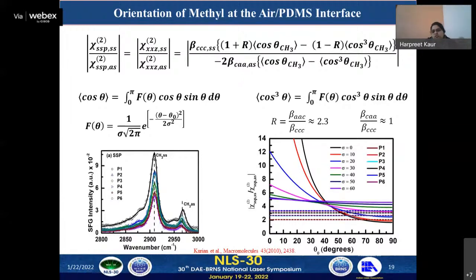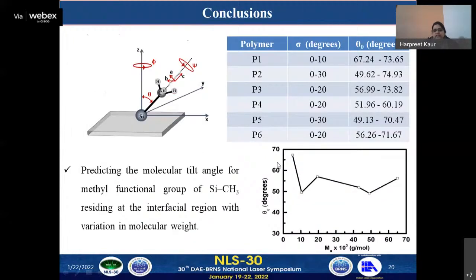So we have determined this for all the polymers, and we have found that there is a decrease in the orientation angle of the methyl group with increasing molecular weight, which actually confirms that the free volume at the interface is decreasing with increasing molecular weight at the air polymer interface.